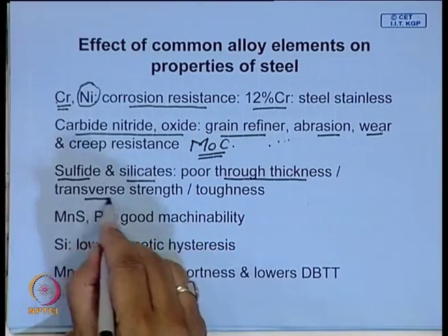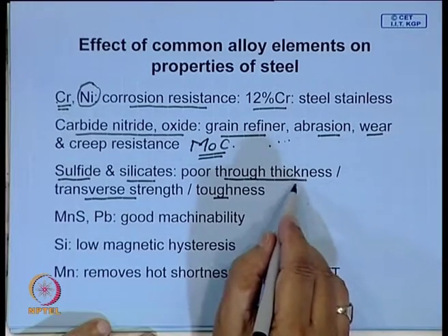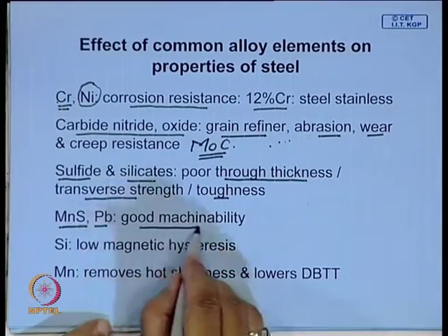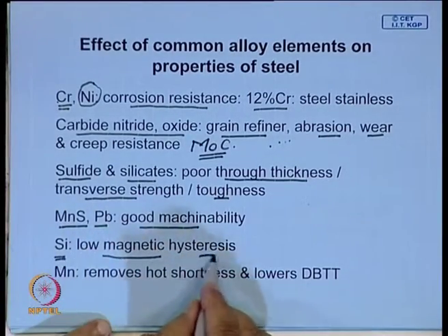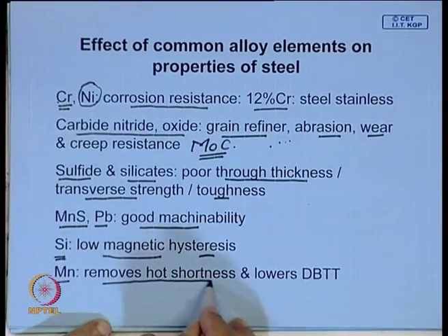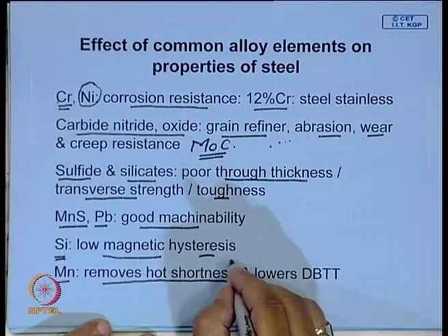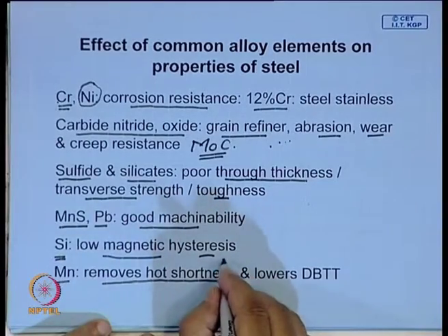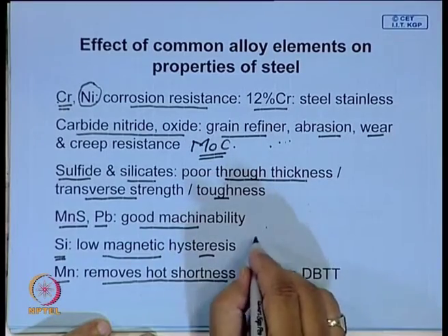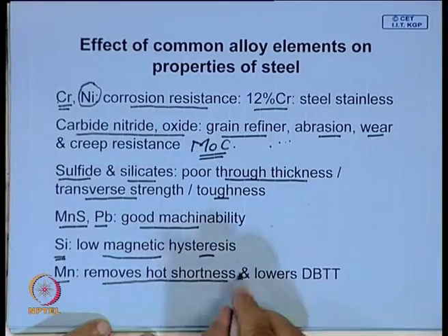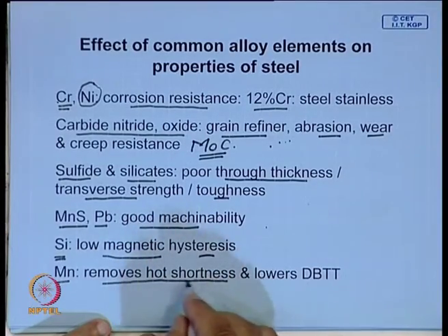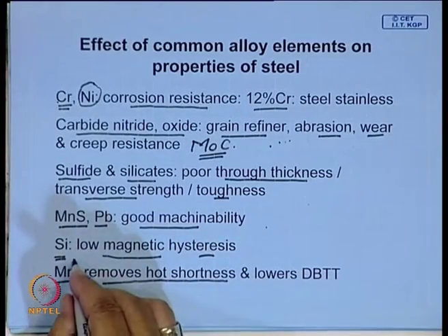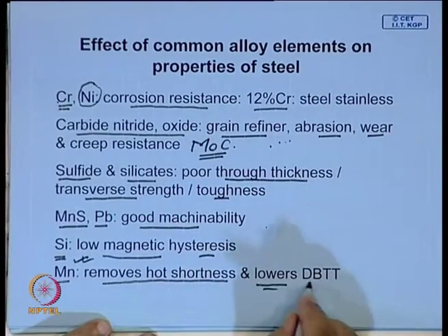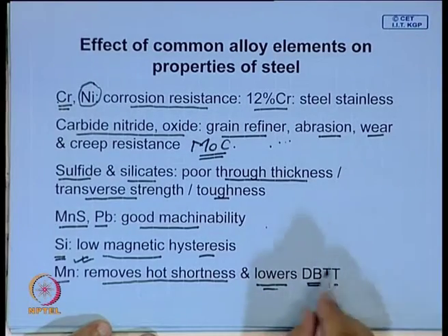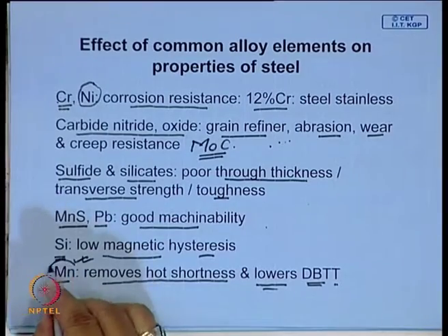Similarly, sulphides and silicates give poor through thickness properties, or transverse strength and toughness. They also give problems with weldability. These inclusions we just mentioned give good machinability. Silicon gives low magnetic hysteresis. Addition of manganese removes hot shortness. We did talk about it, the problem related to sulfur content in steel. Sulfur segregates to grain boundaries, and if manganese is not there, it will form iron sulphide, a low melting eutectic, which gives steel poor hot workability, and this is known as hot shortness. Addition of manganese is extremely important to lower the ductile to brittle transition temperature. All cryogenic grades of steel will have a sufficient amount of manganese.